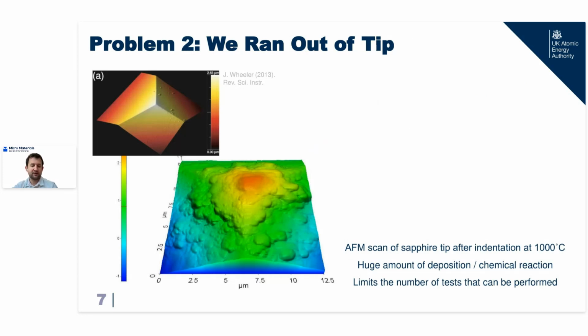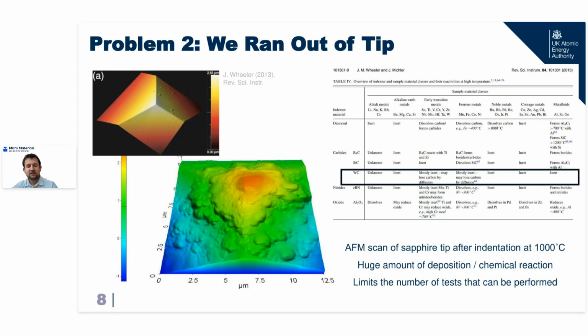So you see this huge amount of deposition, this huge amount of chemical reaction, and that really is what we're finding at these high temperatures is the limiting factor for high temperature nanoindentation. There's a tentative answer that tungsten carbide is probably the best choice for indenter. It's pretty hard. It's not as hard as diamond, but it's still pretty good mechanically. But by and large, what we care about at these temperatures is not mechanical performance, it's chemical performance, and that's where it comes in. As long as you're testing in vacuum, you can use this tungsten carbide indenter, and that shouldn't react with most samples that you're interested in.